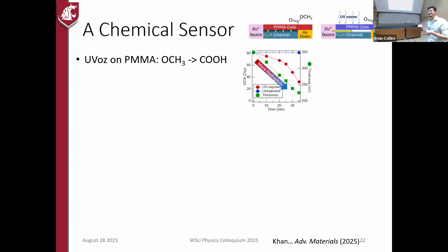Once we were convinced that this was actually happening, we wanted to say, can we use this for something interesting, like a chemical sensor? So Tamada came up with this idea to use a PMMA gate. PMMA, plexiglass, is a hydrophobic material. But we found that there's a nice simple chemical reaction with UV ozone that can, and I'm going to be bad because I don't have a lot of organic chemistry knowledge, change this kind of methyl type group to hydroxyl, and it makes it hydrophilic when you apply UV ozone.